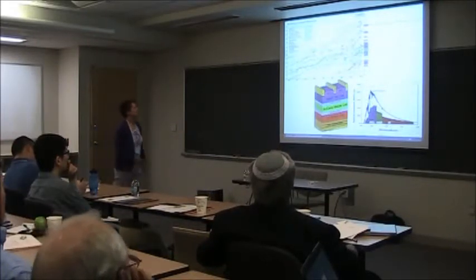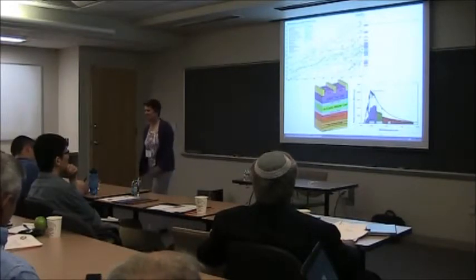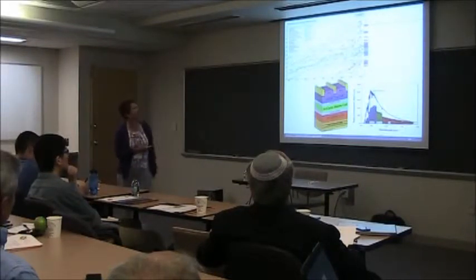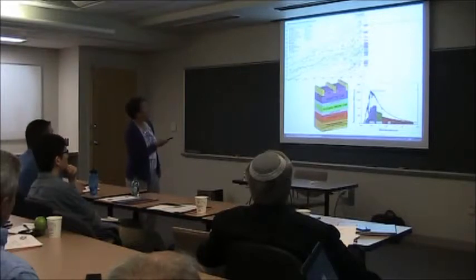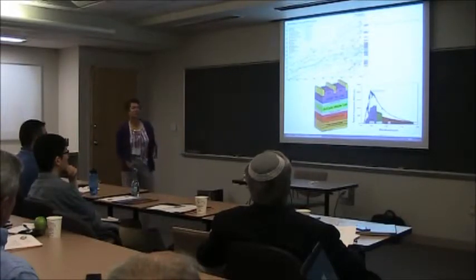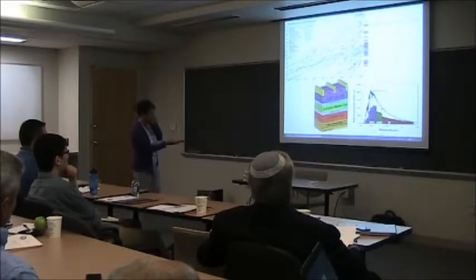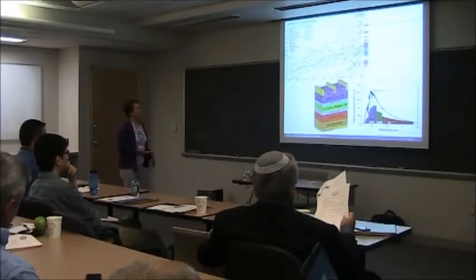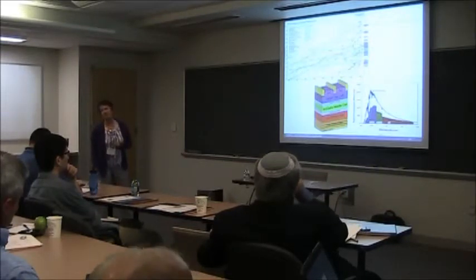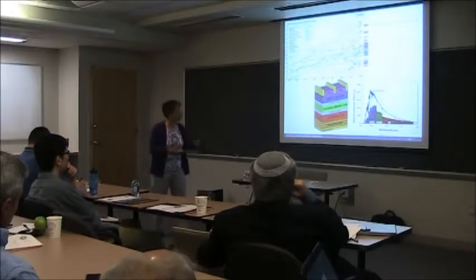Let me just spend 5 more minutes or so on talking about solar cells. If you're from NREL, you have to show this picture. Many of you have probably seen it. It is the famous NREL-maintained plot, but from labs all over the world, of solar cell efficiencies as a function of time. The highest records are held, of course, by multi-junction cells, where they grow, in this case, gallium indium phosphide, gallium arsenide. The lower cell historically has been germanium. These now have efficiencies of 44 to 45%. They're used primarily on satellites. They're also of interest for concentrators. So you take all that sunlight and put it into one very small but very expensive cell.